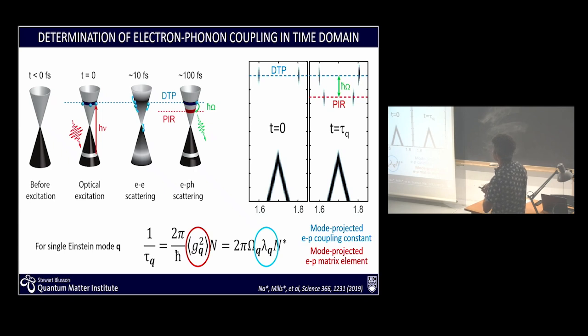You come in, you pump your system, you excite electrons into the unoccupied side of the electronic structure. And now there are two mechanisms that can happen. One is electron scattering, so the electrons relax back down, or electron-phonon scattering, and electrons will relax back down to an energy which is dictated by a particular phonon. Now, working in the time domain, you can use this approach to really extract the electron-phonon coupling or the electron-phonon matrix elements.